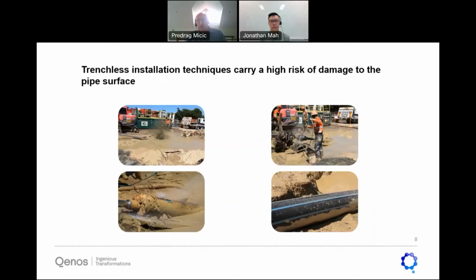So trenchless installations carry a high risk of damage to the pipe surface and the potential for slow crack growth, and the implication of reduced service life must be considered and designed for. And we can see here a few photos from the field. In particular, telling is the bottom right photo, which shows the pipe coming out of the hole during HDD installation, and the clear score or notch on the pipe is visible. So it's a post-event, very hard to do anything with it.